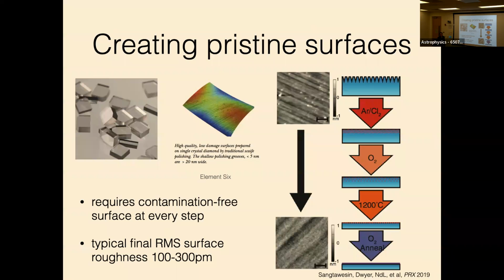And we have to do reactive ion etching to remove the polish damage. That leaves behind some etch damage, which we then have to etch away with a different etch. That leaves behind its own etch damage, which we then have to anneal away with high temperature annealing. And then we have a final oxygen annealing step to create our last surface.